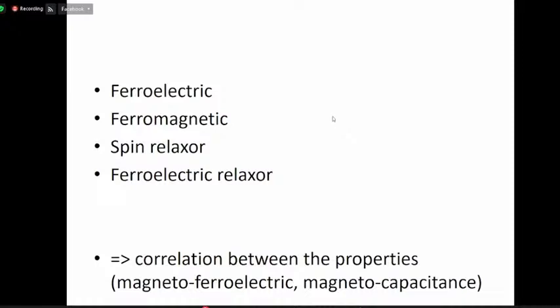Until now, we see ferroelectric, ferromagnetic, spin glass, and ferroelectric relaxor behavior in these materials. It's quite wonderful because we used just an antiferromagnetic insulator, but they show quite emergent properties in these materials.